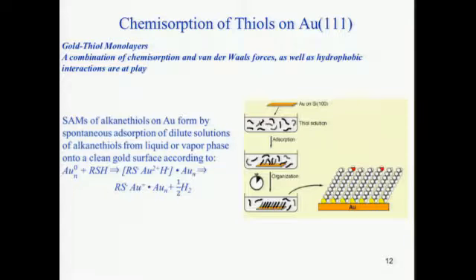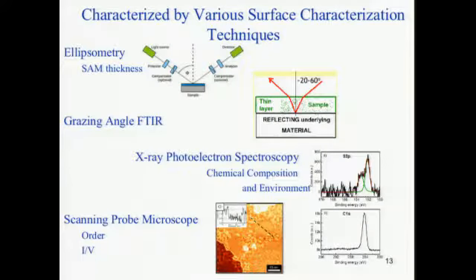Basically, it's a chemisorption, and it's pretty simple. It's really simple chemistry. You have your gold surface, and it's a thermally evaporated gold on the surface. And then you introduce that to a dilute solution of your molecules, and over some time you get an ordered structure.